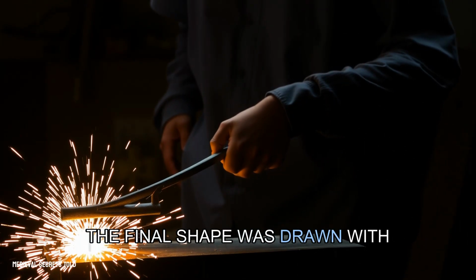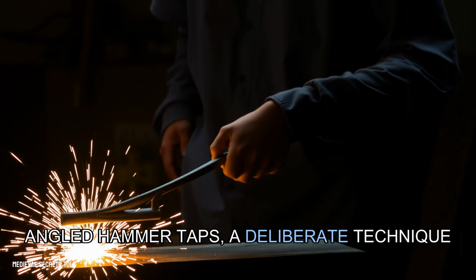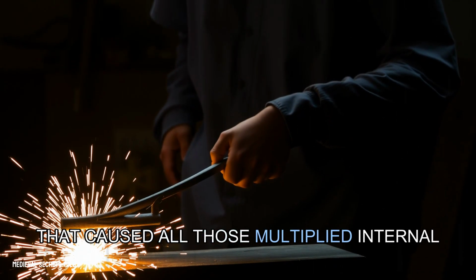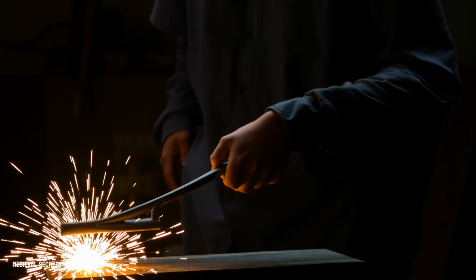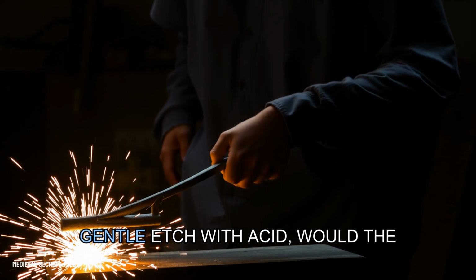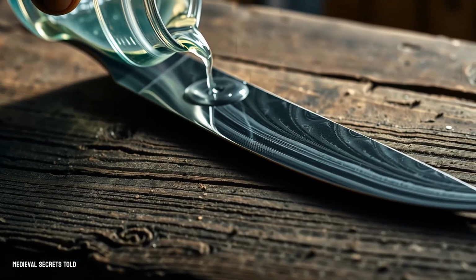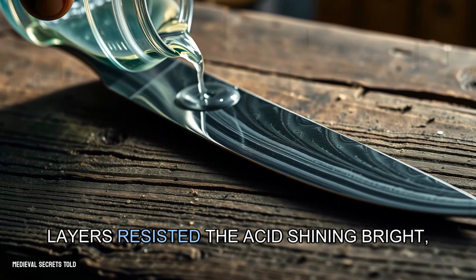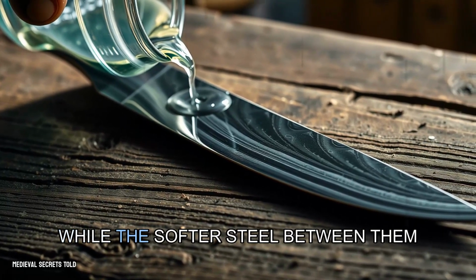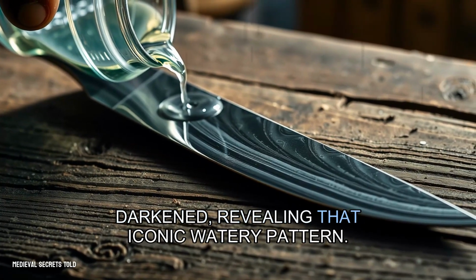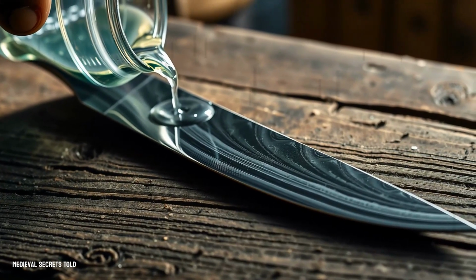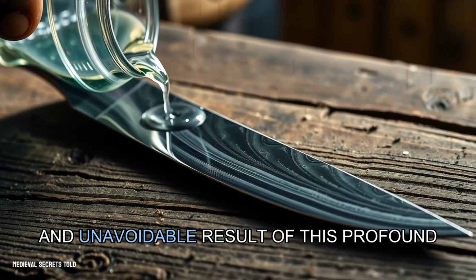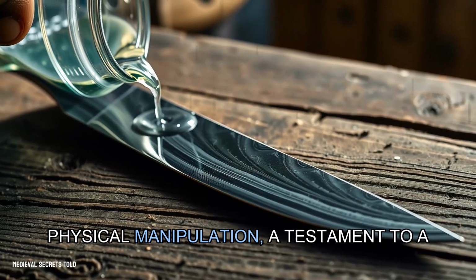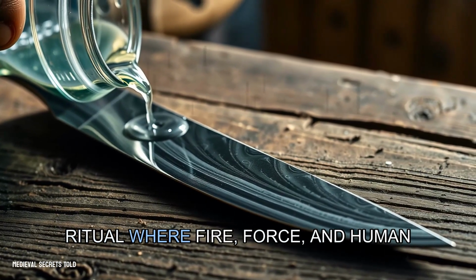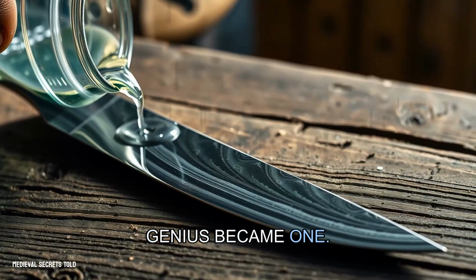The final shape was drawn with angled hammer taps, a deliberate technique that caused all those multiplied internal layers to intersect the blade's surface in a flowing, wavy topography. Only then, after polishing and a gentle etch with acid, would the secret finally become visible. The hard layers resisted the acid, shining bright, while the softer steel between them darkened, revealing that iconic, watery pattern. The beautiful design was the direct and unavoidable result of this profound physical manipulation, a testament to a ritual where fire, force, and human genius became one.